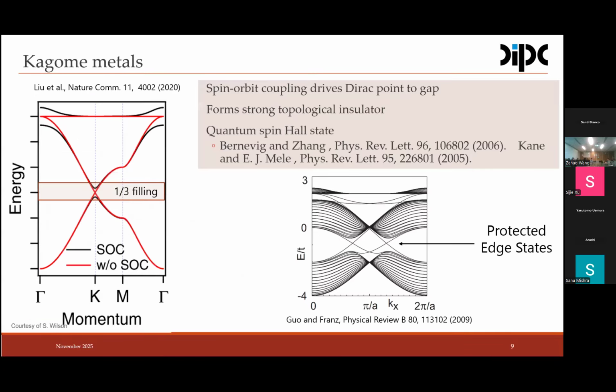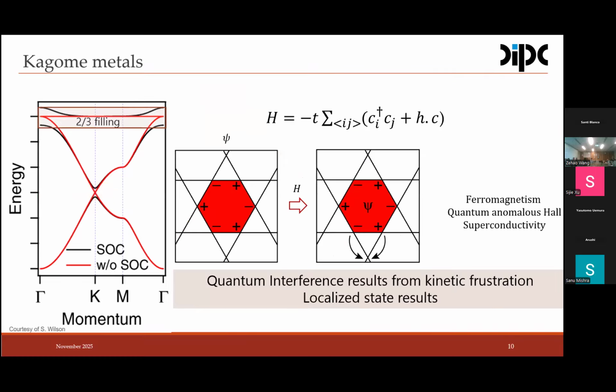But anyway, what we can do, and we can play around with the Kagome materials, is to tune the chemical potential through the Van Hove singularities, Dirac crossings, and flat bands. So, for instance, if the chemical potential falls into the Dirac crossing and the spin-orbit coupling opens the gap, we can end up with topologically protected edge states. If you put the chemical potential exactly at the flat band, this flat band arises from the destructive interference of the electronic wave function.